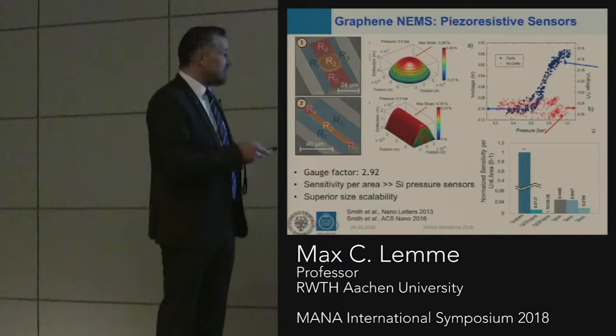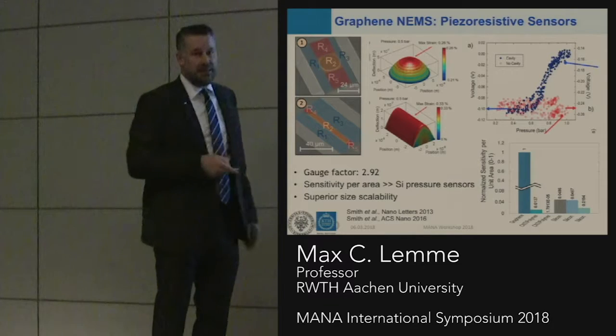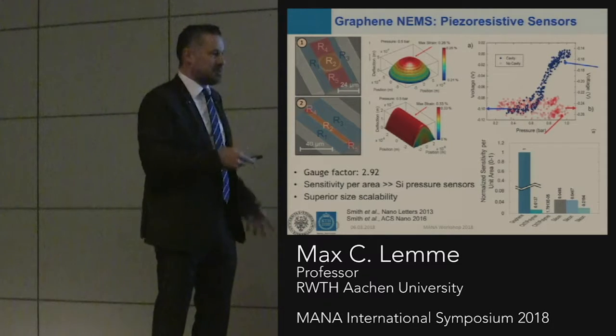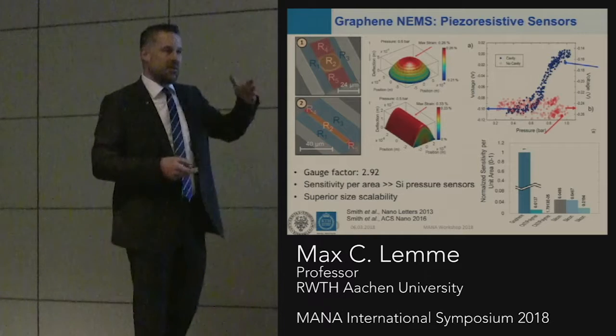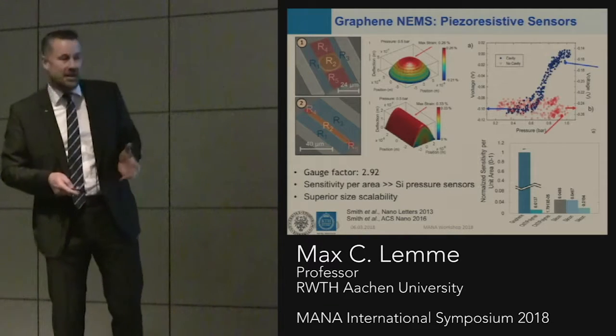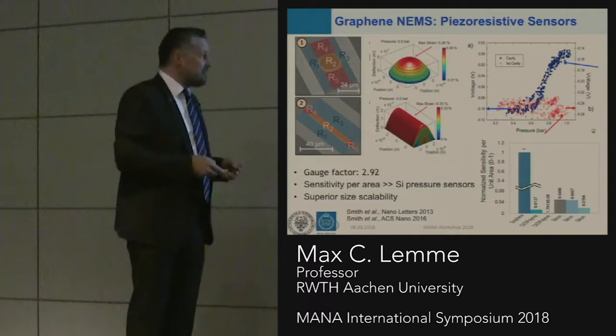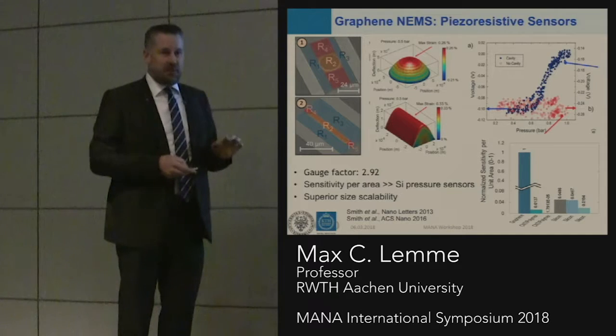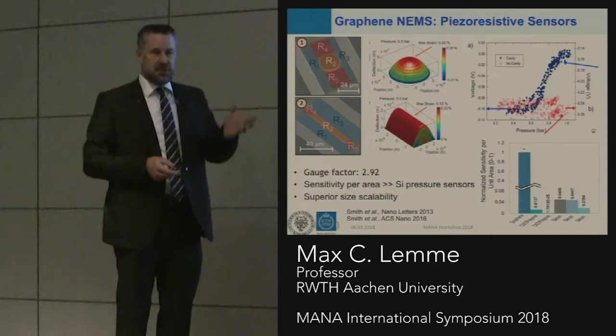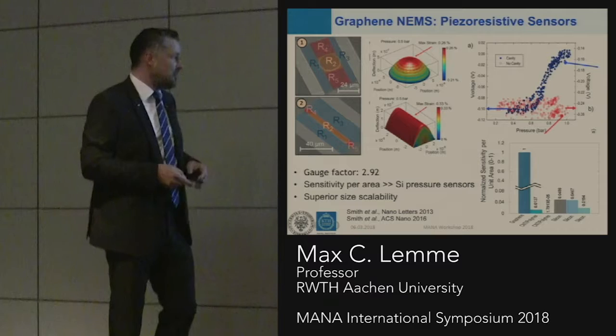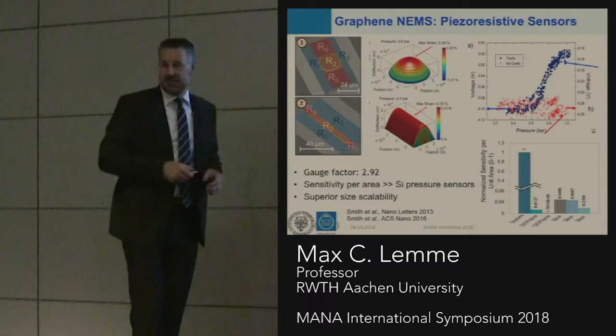And this is all despite a low gauge factor of around 3 for graphene. This is actually not a high number, it's almost like a metal - not surprising, it's a semi-metal. But at the end of the day, the thickness or thinness of the membrane, which is only 1 atomic layer, less than a third of a nanometer, makes it very size scalable.